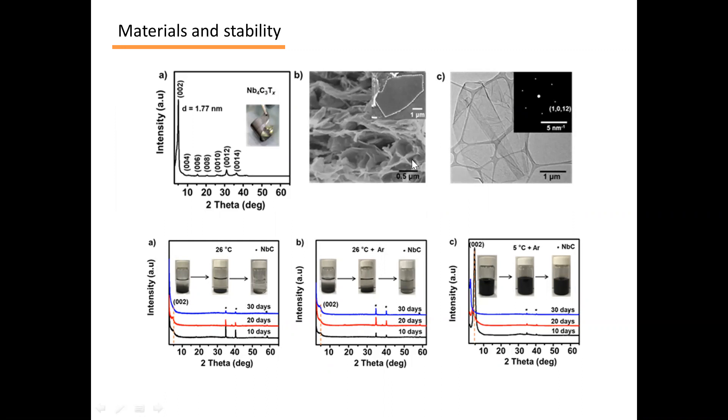Some MXenes tend to be oxidized in air or aqueous environment, which is detrimental for practical use. It is important to find suitable storage conditions for MXene solutions. In this paper, as-prepared Nb4C3 suspensions in distilled water were separated and stored in different conditions, then a part was collected and tested by XRD regularly. According to the results, the deaerated Nb4C3 solution can be stored more than 30 days when refrigerated.